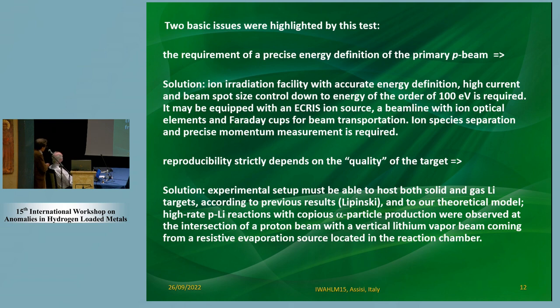So what are essentially the conclusions? The requirement of precise energy definition of the primary proton beam. We need an ion irradiation facility with accurate energy definition, high current, beam spot size control, down to energies of the order of 100 electron volts. It may be equipped with an electron cyclotron resonance ion source, a beam line with ion optical elements and Faraday cups, all standard equipment. We need ion species separation, precise momentum measurement. All these elements are absolutely necessary if you want to characterize the phenomena.